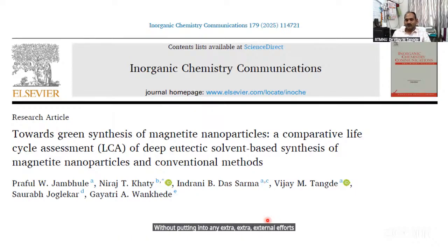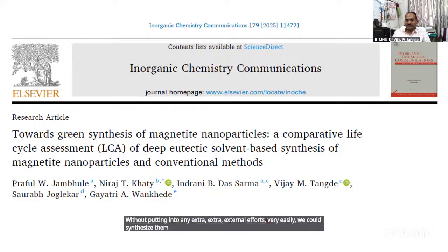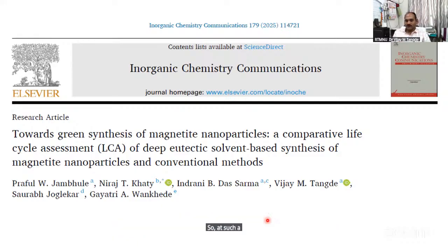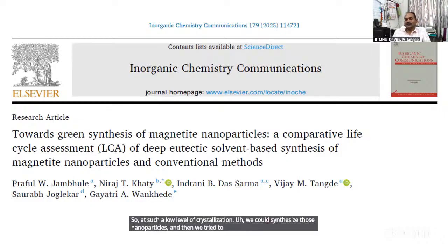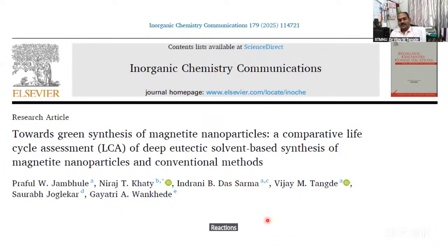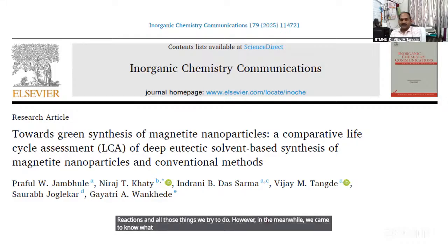Very easily we could synthesize them, and we saw the size of the nanoparticles came down to 1.3 nanometers. So at such a low level of crystallization, we could synthesize those nanoparticles, and then we tried to use them in different processes. We used them in Biginelli reactions and all those things. However, in the meanwhile, we wanted to know what is different in our synthesis.